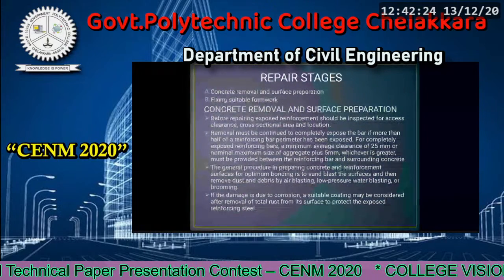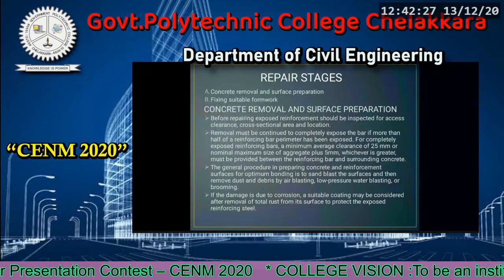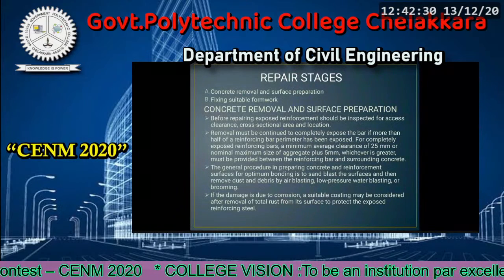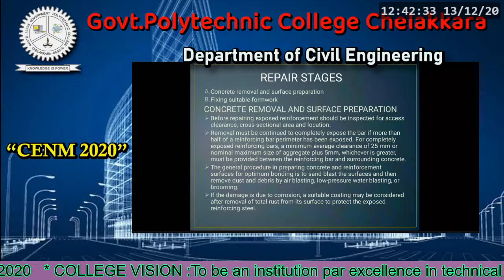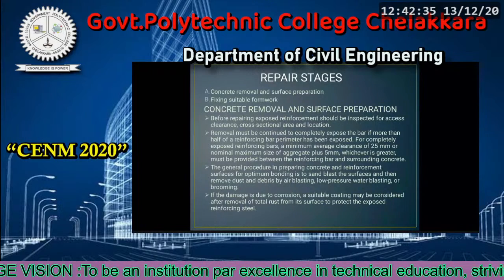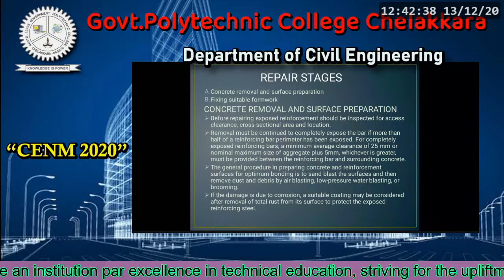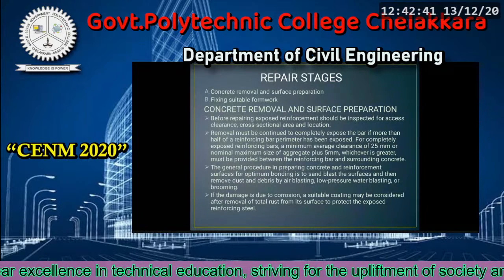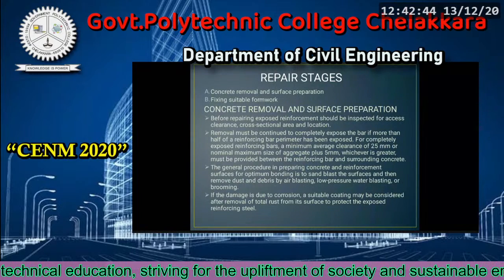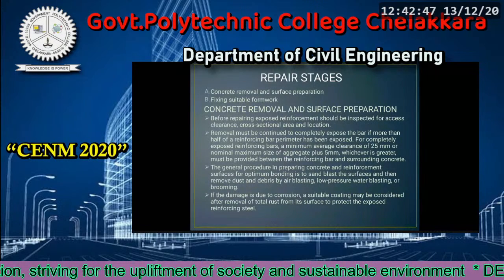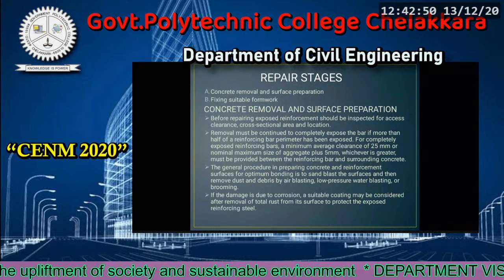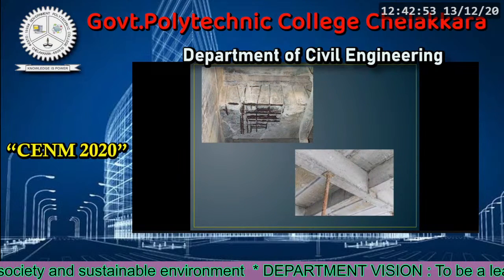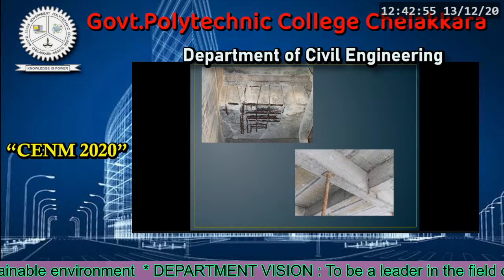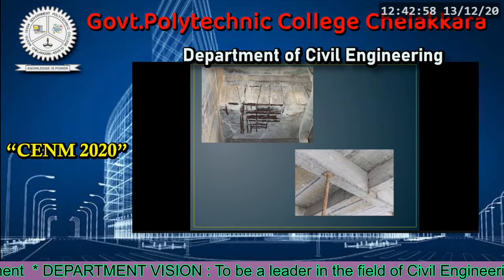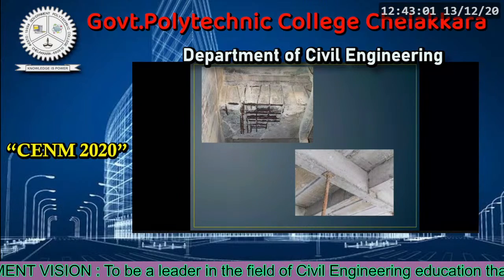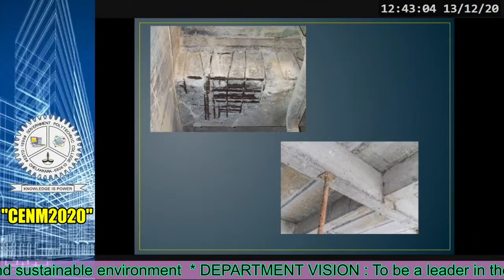The area which is to be repaired, to be cleaned for optimum bonding, is to be sandblasted and then dust and debris removed by air blasting, low pressure water blasting, or brooming. If the damage is due to corrosion, a suitable coating may be considered after removal of total rust from its surface to protect the exposed reinforcing steel. So in this picture, in the first picture we see the reinforcing bars are exposed at the outside. So in this, we should clean the excess concrete and then replace it, as in the second picture.